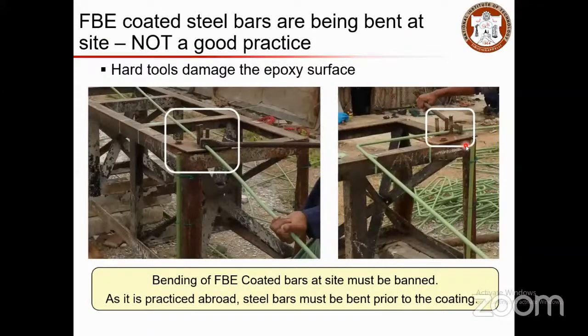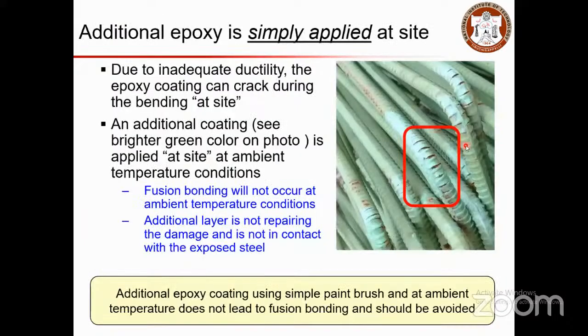But here you can see you have a straight bar, and the practitioners just want to use this as stirrups, and they are bending it at the site. When you bend it, the bent regions are going to crack, because you have some epoxy material on top of the steel, and when you bend it, the steel can withstand the bend, but the coating cannot, and that will cause cracking on the surface. Such cracking is going to accelerate the corrosion process by inducing more anode and cathode, or the ratio between the anode and cathode will be higher, and that will accelerate the problem.